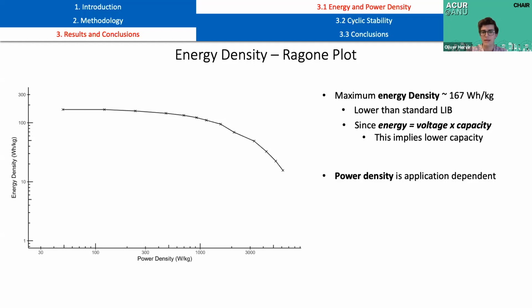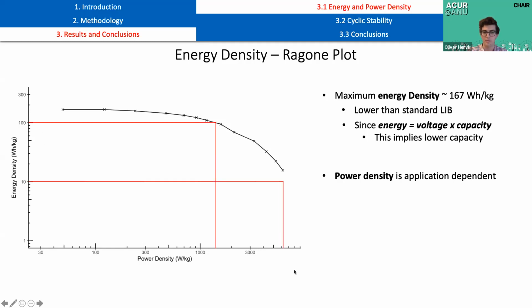We can also learn about the power density of our battery. Now, power density is application dependent, by which I mean, if I need an energy of 100 watt-hours per kilogram, clearly I can have any power underneath 1,500. But if I only need 10 watt-hours per kilogram, I have access to a larger range of powers. But despite this application dependency, it's still overall lower than a standard lithium-ion battery. And this was a little bit unexpected, given that the anion PF6, which the dual-ion battery uses, is able to diffuse very quickly through solution and into the electrode.